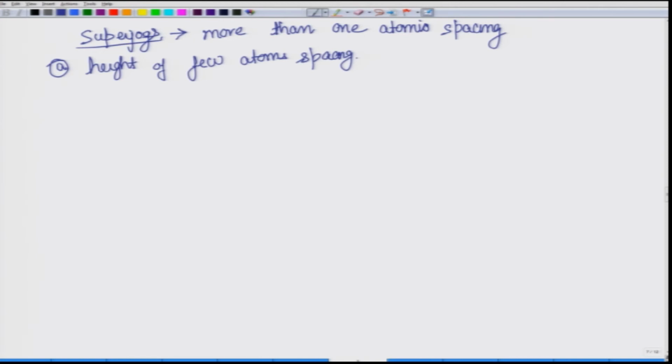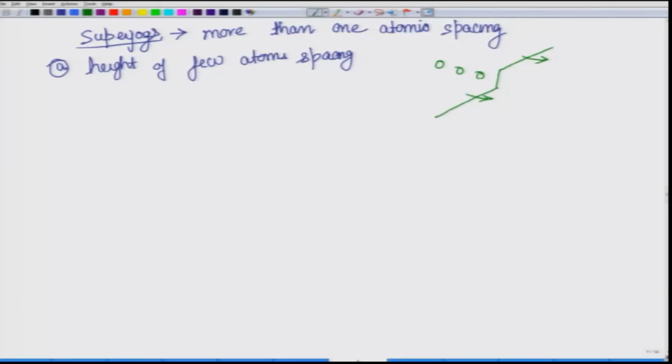In this particular case, you have something like this screw dislocation, there is a jog which is a little larger in size, and if the whole thing is moving, this will also drag the edge dislocation, however, leaving a trail of vacancies behind. So, this can move. What we are trying to say is that when it is a few atoms thick, it can still move, and when it moves, because this is a climb of the edge dislocation, it will leave behind a trail of vacancies.